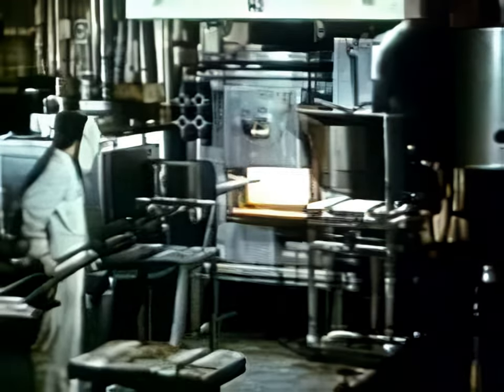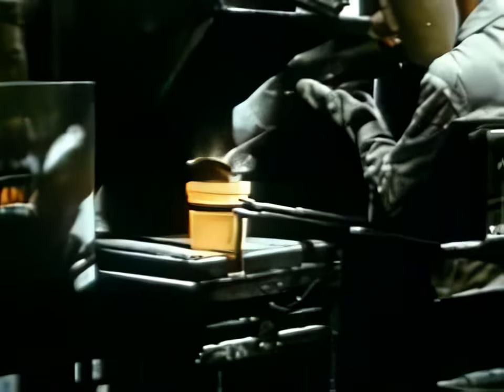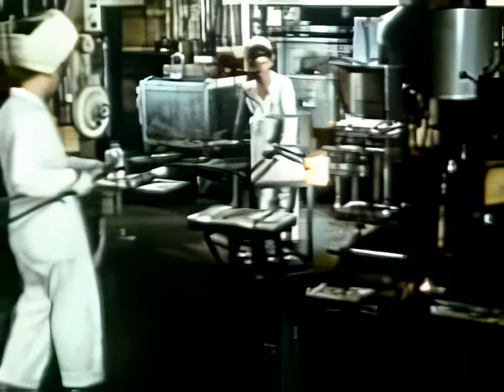After the ingredients have been thoroughly mixed in the tumbler, the next step, charging the crucibles, takes place. 3 parts by volume of the dry chemicals melt down to 1 of the molten glass. The crucibles in the clay pots are made of platinum, and each one is worth many thousands of dollars. But it's not an extravagance. The platinum lasts indefinitely, and more important, since it does not oxidize at the high temperatures used here, the glass is completely free of impurities.